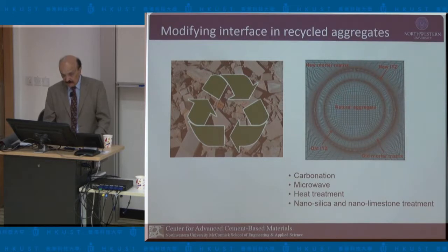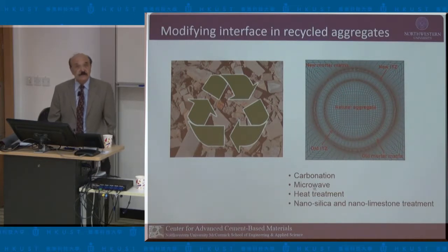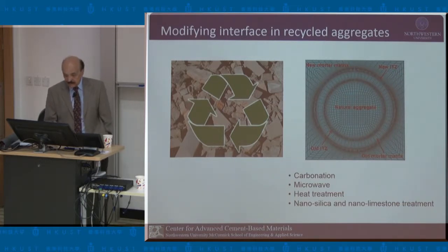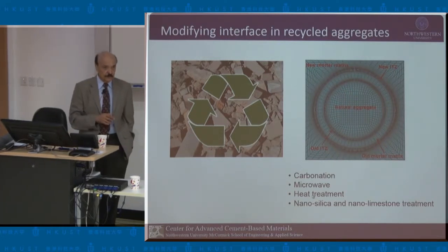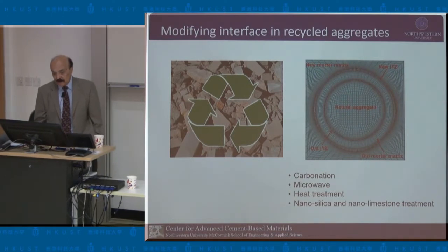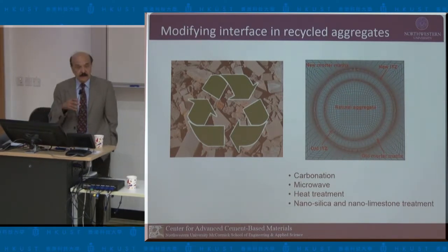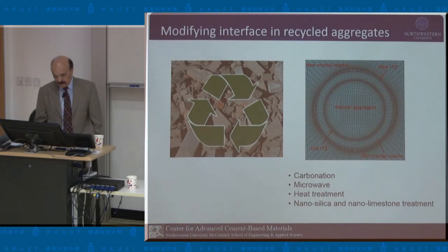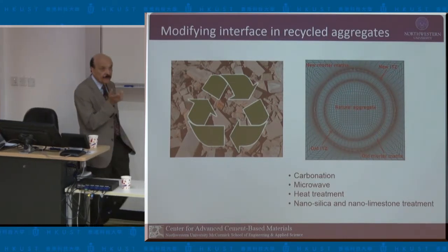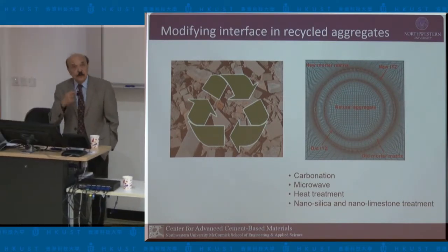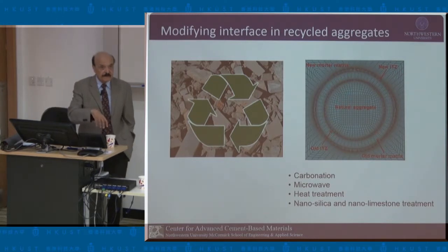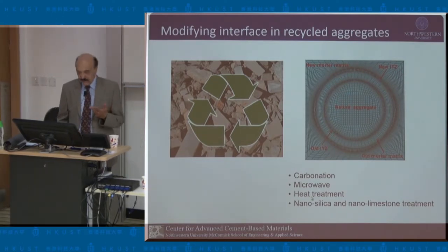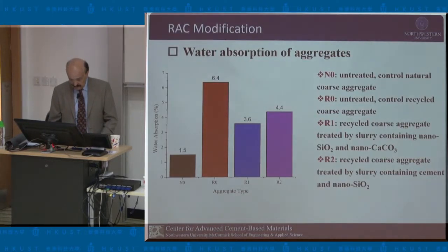One approach is carbonation by C. S. Poon at Hong Kong Poly, that is, carbonating the surface. In Singapore, they're microwaving it to remove that old mortar. Harry Yong is doing that. Some people in India are applying heat to that old mortar. We have started a project jointly with Zhejiang University, Hangzhou, asking can we modify the surface by dipping it in nanosilica or nanolimestone. So I want to present some results of that work here.